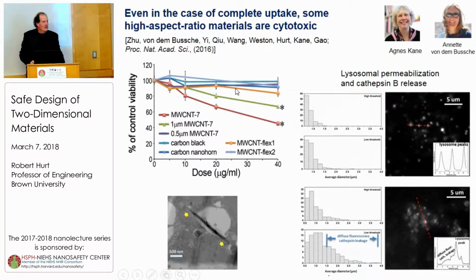And this data shows that if you take a long, stiff carbon nanotube, it's cytotoxic. If you take a variety of particulate forms of carbon, regardless of their shape or detailed structures or surface chemistries, they seem to be non-toxic in this assay. And then we undertook to progressively shorten the nanotubes and see if we could make this toxicity go away. Was it really length dependent?